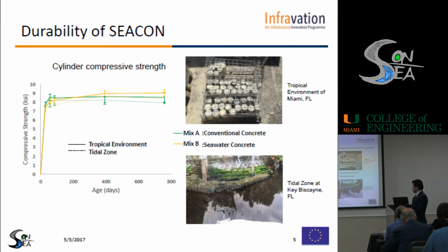And then we go to the second environment, which is the tidal zone. Again, we had the opportunity to expose our samples in Key Biscayne, Florida. We just put those cylinders in boxes, and then we exposed them to the tidal zone. They have been there for 2 years. We went there and took out our samples after a year, and then after 2 years.